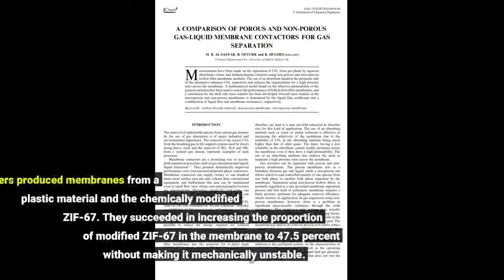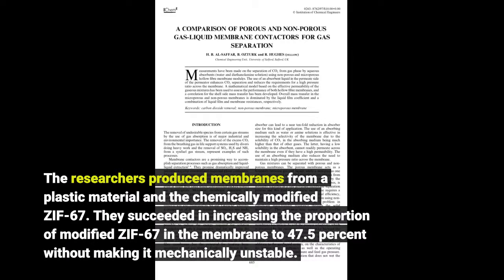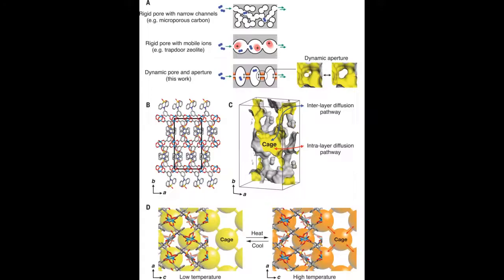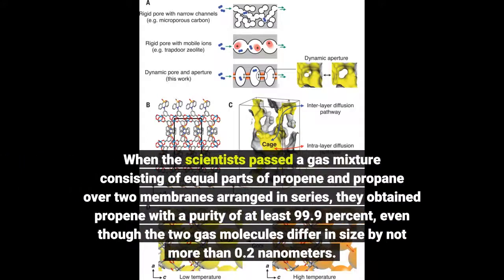The researchers produced membranes from a plastic material and the chemically modified ZIF-67. They succeeded in increasing the proportion of modified ZIF-67 in the membrane to 47.5% without making it mechanically unstable. When the scientists passed a gas mixture consisting of equal parts of propene and propane over two membranes arranged in series, they obtained propene with a purity of at least 99.9%, even though the two gas molecules differ in size by not more than 0.2 nanometers.